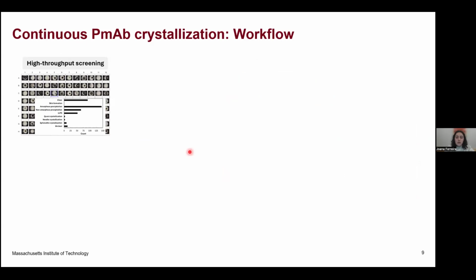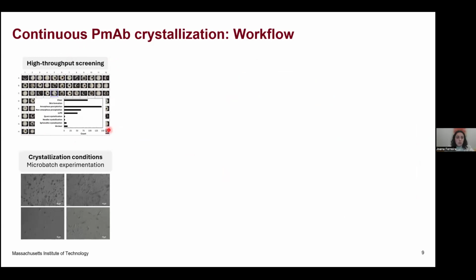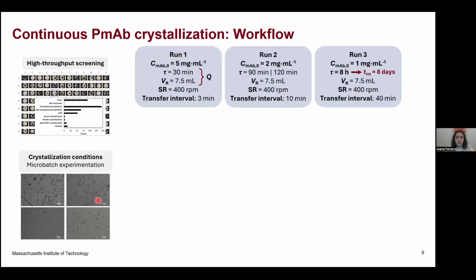The second example that I'm showing is the most recent work, with a different mAb. So the same strategy: we start with the high throughput screening. We try to get our first good hints where we can see some crystal formation. Then we start scaling up from sitting drop to micro batch. And then we can think about the continuous process. For this specific mAb, we did 3 different runs: 3 different initial supersaturations, 3 different residence times, but always keeping the same reactor volume, less than 10 ml.